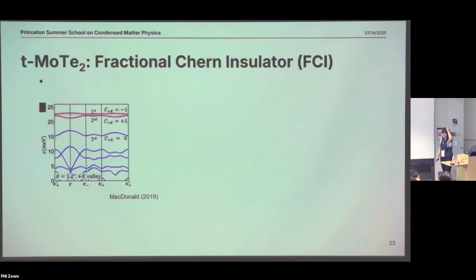And so we recently measured this twisted molybdenum, which is a fractional Chern insulator that was first demonstrated by our collaborator at UW, Zhurun's group. And it all began with the MacDonald model, Allan's model, on the topmost valence bands of twisted molybdenum, because the band was flat enough, the kinetic energy was suppressed enough, and also because there's non-trivial topology of the bands due to this skyrmion type of texture.